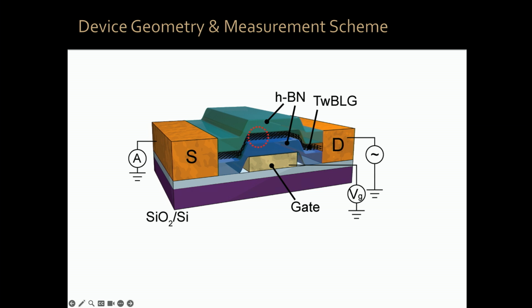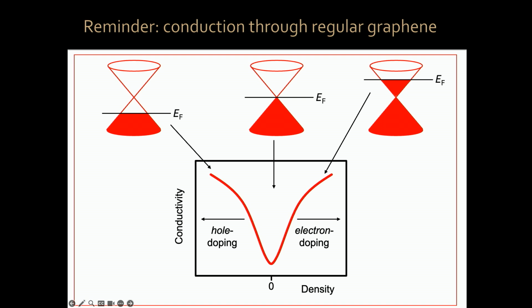So before I show you actual data of what conduction through magic angle graphene looks like, let me remind you, or show you, probably for some of you for the first time, what conduction through regular graphene looks like. Yeah? So if you measure the conductivity of graphene versus density of electrons, if your Fermi energy is deep into the valence band, you have lots of holes here, and those conduct very well, so you have high conductivity. If your Fermi energy is deep into the conduction band, you have lots of electrons, and therefore you also conduct very well. If your Fermi energy is near the charge neutrality point, you don't have many charge carriers, and therefore it conducts poorly. So the conductivity of graphene versus density looks like this V shape. Yeah? And this has been measured by thousands and thousands of groups around the world.